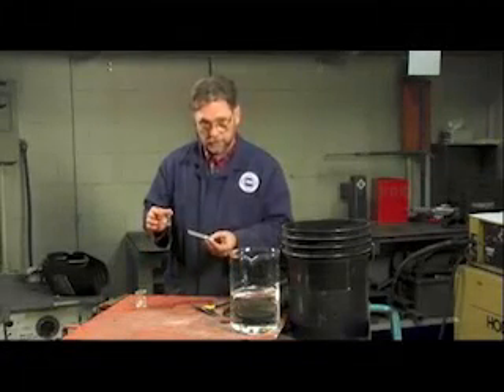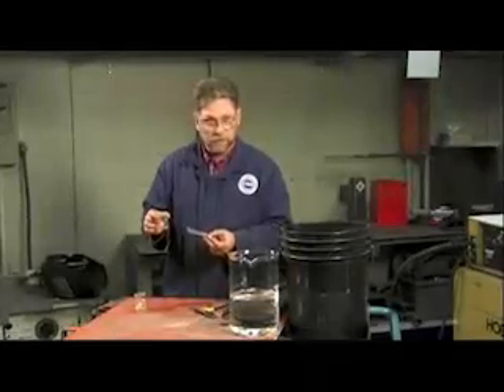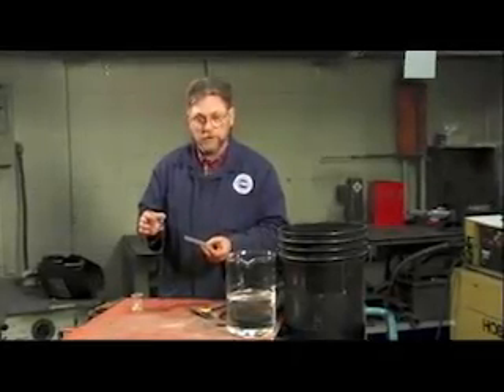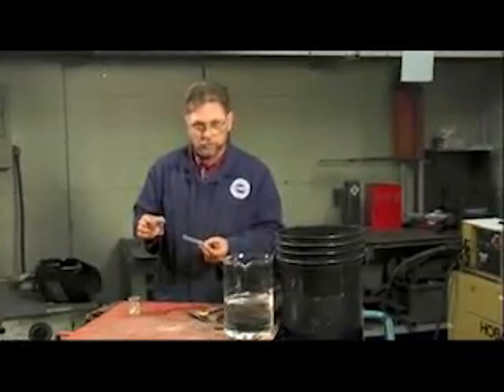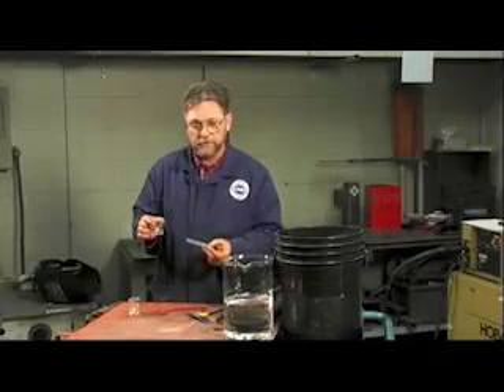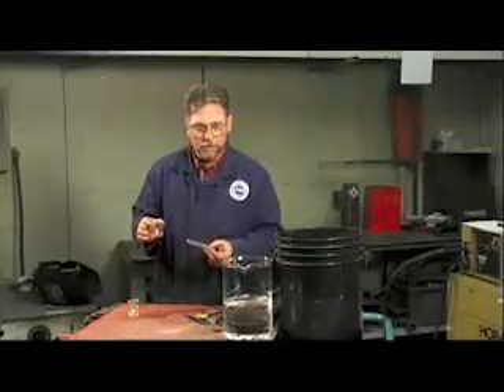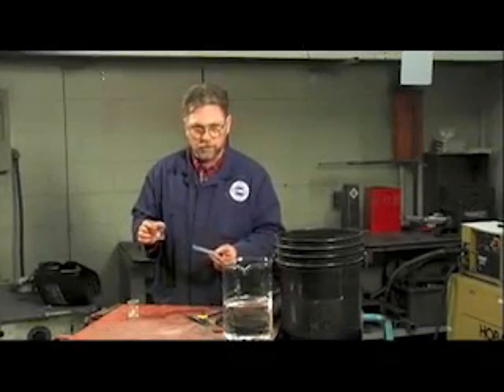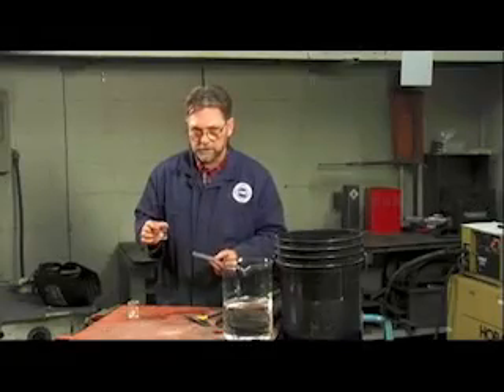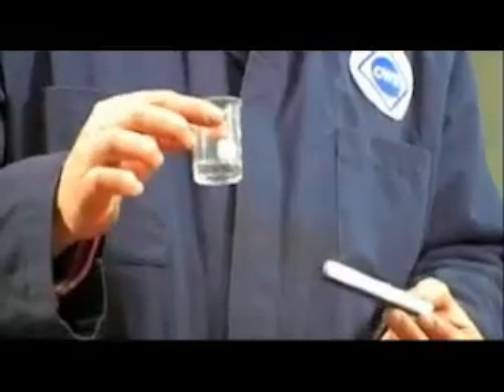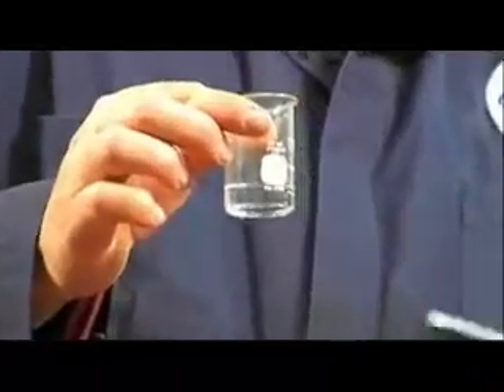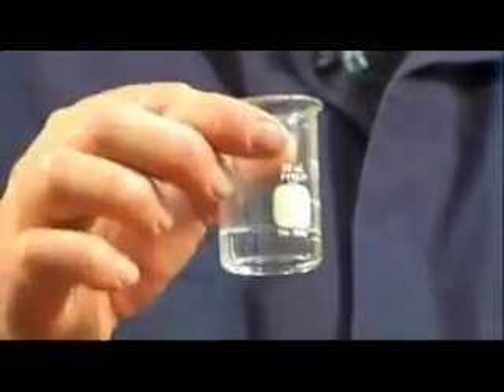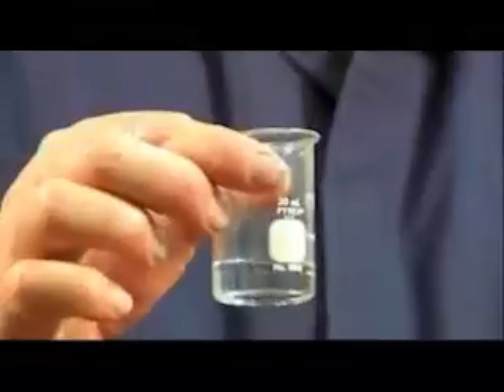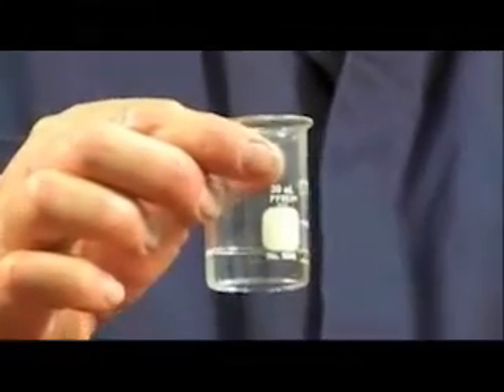If we change electrodes to a basic low hydrogen electrode that's been handled correctly, that is, that it's been left in its hermetically sealed packaging, or has been kept in heated storage at above 120 degrees Celsius, we find that the amount of hydrogen that would have come out of this much weld metal will be something less than 10 milliliters for every 100 grams of weld metal that's produced.